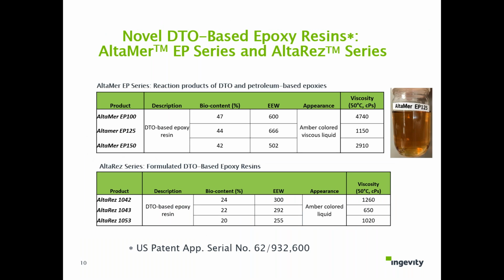Now let's talk about Ingevity's new DTO-based epoxy reagents. AltaMer is an Ingevity trade name for bio-based monomers and oligomers. AltaRez is an Ingevity trade name for new bio-based polymers and reagents and formulated materials ready to use. So you can see in the first table, we developed 3 AltaMer EP epoxies, EP100, EP125, and EP150, all DTO-based epoxy resins. Bio content ranges from 42% to 47%, EEW from 500 to over 600, and they are room temperature viscous liquids, with viscosity measured at 50 Celsius from 1,000 to somewhere around 4,700 centipoise.